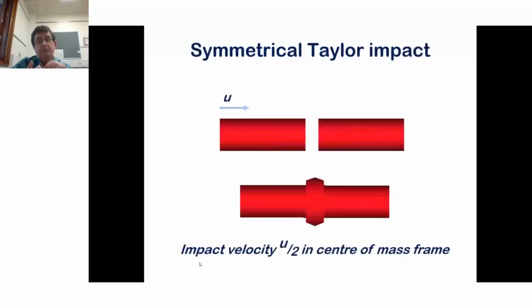You can do a thing called symmetrical Taylor analysis, where we have a rod hitting a rod of the same material. That is useful for two reasons. Number one, if you're doing modeling, the center of mass of the experiment is always between those two rods. And also, as the rod deforms and spreads outwards, the rods expand at the same rate. They're the same material, so friction doesn't have any effect because they're moving outwards at the same rate. There's no friction between them. Simpler arrangement in terms of analysis, a little bit more irritating when you come to set it up.